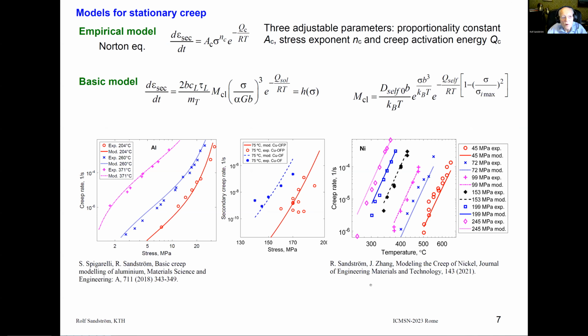Now, the empirical model for stationary creep is the Norton equation. It describes the stress dependence of the secondary creep rate. It also takes into account the temperature dependence. And there are 3 adjustable parameters: the proportionality constant, the stress exponent, and creep activation energy. This equation can describe quite a number of experimental results.